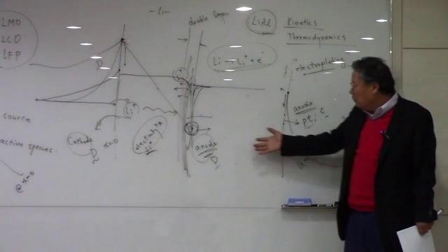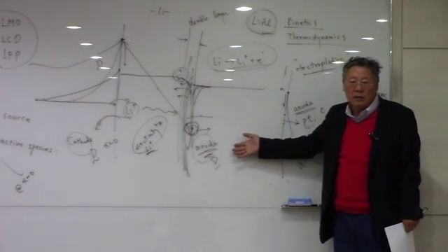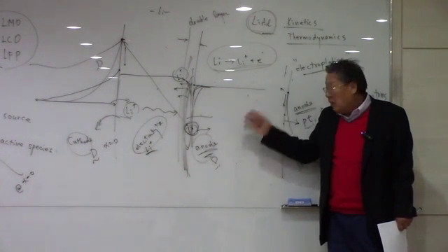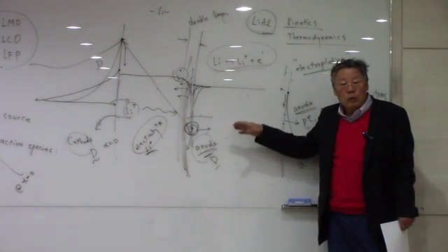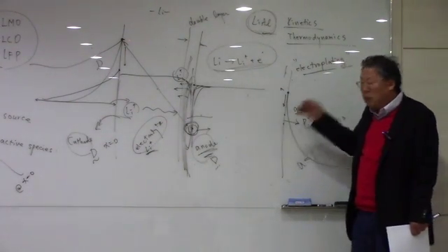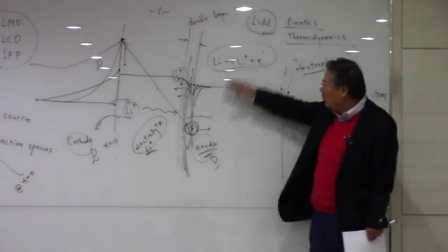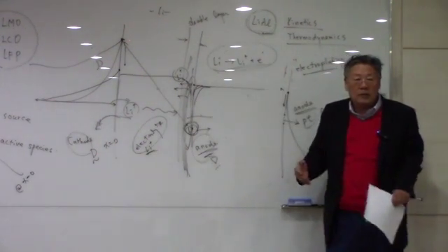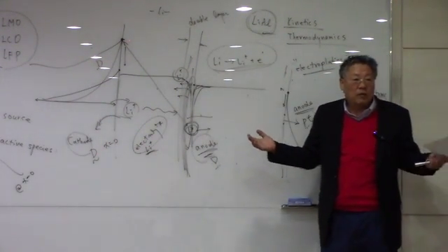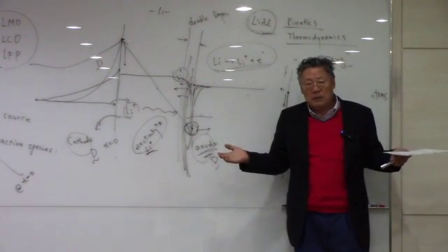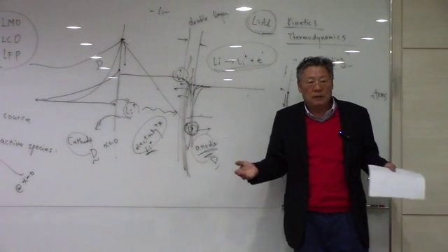But why do people work on developing new compounds for the anode? Because, for instance, in the case of lithium, if you use pure lithium, then everything has to be fabricated in a dry box, an oxygen-free, moisture-free environment. Very costly, okay?